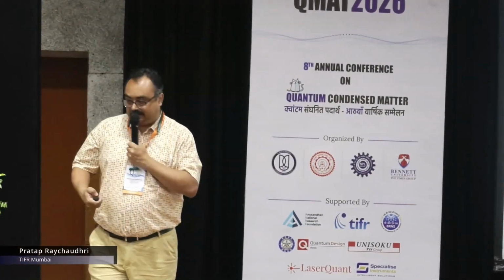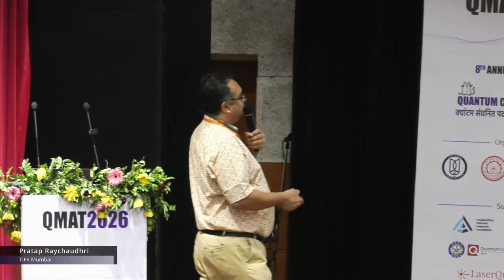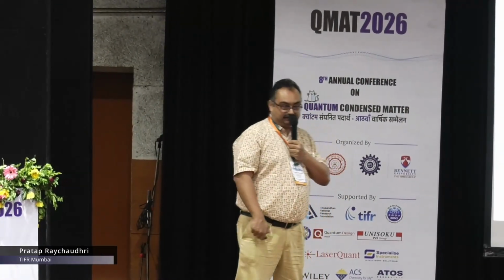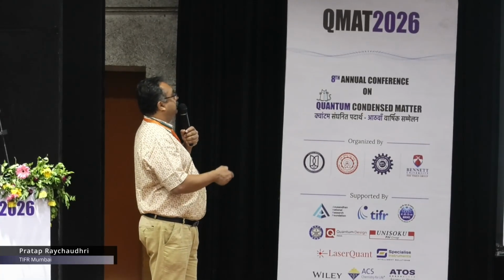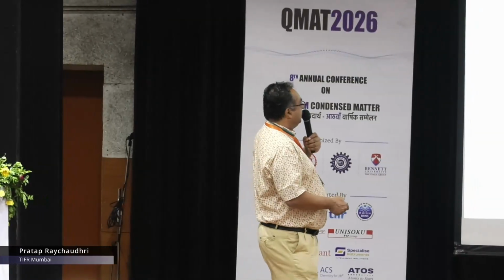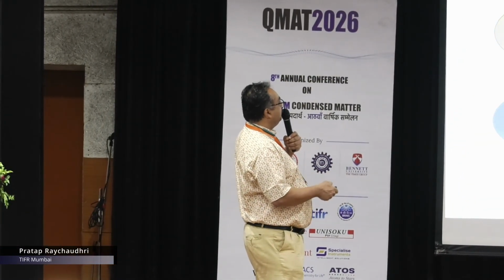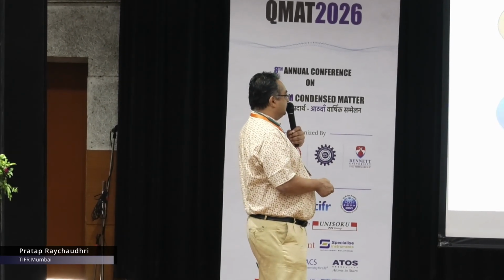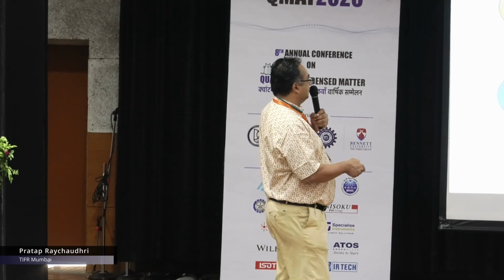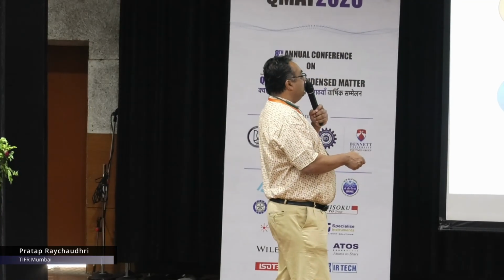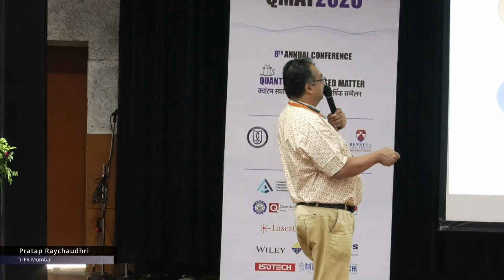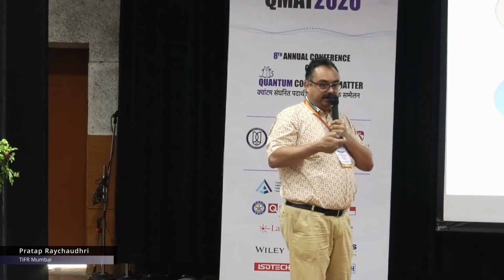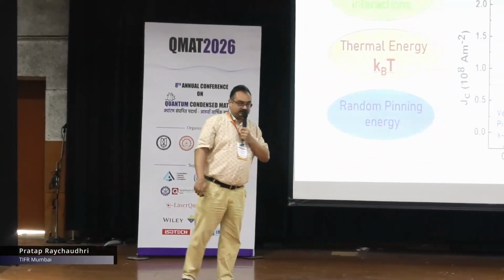Okay, so now we want to study a situation where I will have all these energies competing with each other. So I had earlier taken a limit where at least one of these was not important. So for that, what we do is that we go into something which is moderate pinning. Now this is the critical current density of the films that we have studied. You can see the very weakly pinned molybdenum germanium film is this one here, and the reasonably strongly pinned, this is the critical current density for the 5 nanometer rhenium zirconium. Now what I do is that I increase the thickness of this rhenium zirconium film to 20 nanometer. So effectively I reduce the pinning and I have a critical current density which is intermediate between the two. You have to look at low field. At high field there are additional effects that come in from interactions.